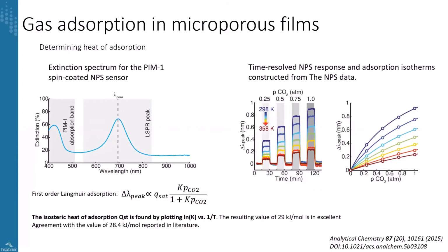So once again monitoring the peak position, but also the absorption band of the polymer that was spin coated on the surface. The researchers used time-resolved NPS and its response to calculate adsorption isotherms, and they did that also while changing the pressure of CO2, the partial pressure of CO2, but also the temperatures. And a combination of all these allowed them to calculate the isosteric heat of adsorption, which is a very good indicator of how a gas is being adsorbed to a material.